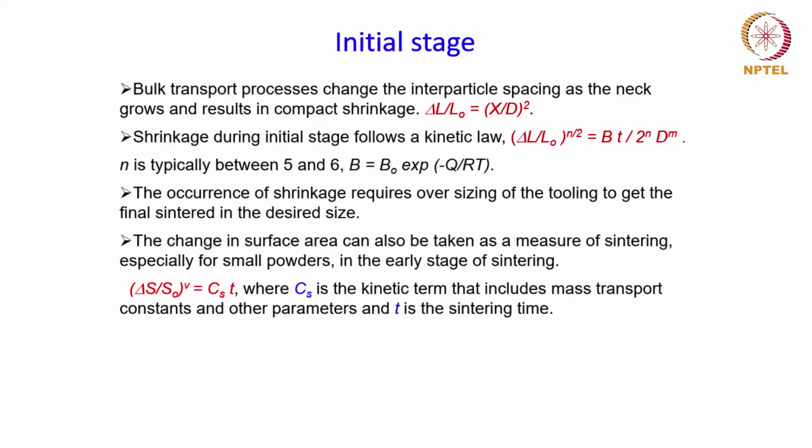So in the initial stage, kinetically, if you see, the densification scales with 1/3 power of time, as you can see from this particular equation over here. And the change in the surface area can also be taken as the measure of sintering, and that is given over here by this equation. So now let us see, as we progress to the next stage of sintering, what happens in that.